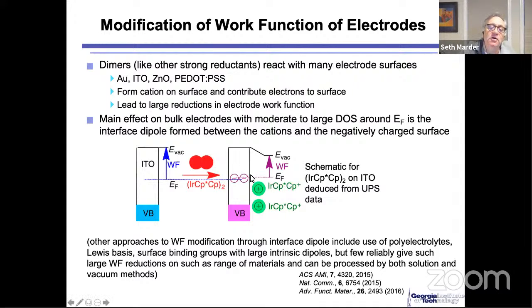So when you do that, you create what's called an interface dipole, and that interface dipole leads to a shift in the vacuum level. And as you know, the work function is defined by the difference in energy between the Fermi level and the vacuum level. And so if you shift the vacuum level down by creating this interface dipole, then what you would expect to see is a reduction in the work function. And what I'll point out is that for electron transport materials, you want materials that have a relatively low work function in order to inject charges.